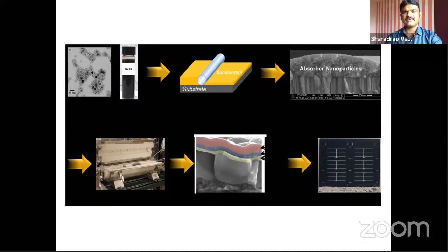These thin films, we sulfurize or anneal by using a furnace. And then in the fifth and sixth figures, you can see how the solar cell can be produced. In the third figure, you can see very small particles, known as nanoparticles of that CZTS. And in the fifth figure, after annealing, you can see the development of nanograins from these nanoparticles, and then you can deposit back-end processes, back-end chemicals, to produce a solar cell.